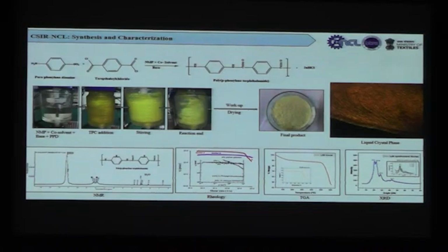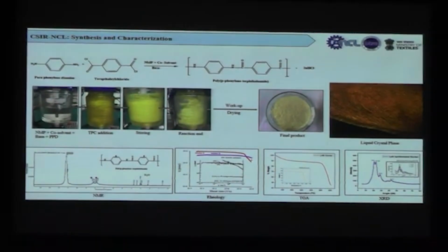Each step is filled with a lot of challenges, especially this being a rigid aromatic structure that does not dissolve in any solvent. So the polymerization is also a challenge at each scale. Currently, after 1 year of rigorous work, we are at a scale where in the lab we can produce 50 gram scale of the required viscosity. For spinning, this rigid rod polymer needs to have a particular concentration, but if you increase the concentration, viscosity increases and spinning becomes difficult.